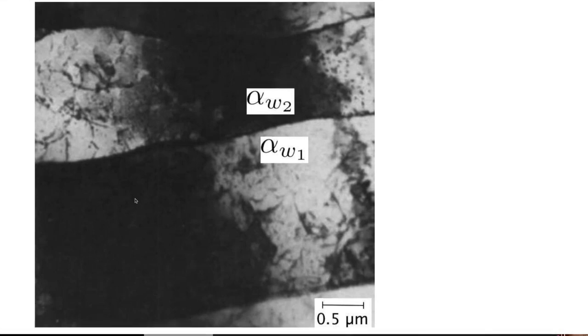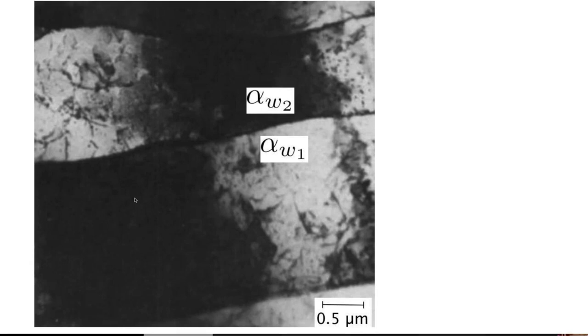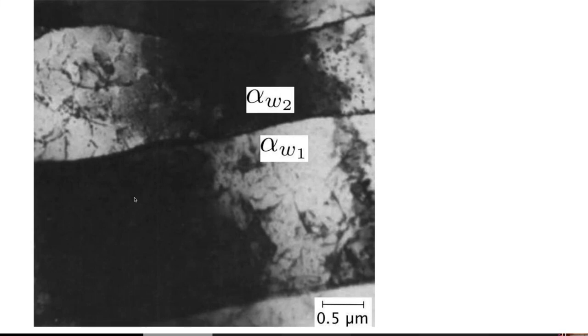Now, you might ask, why doesn't martensite or why doesn't bainite grow by this mechanism? Because they can cancel out each other's strain energy approximately. Well, the reason is there is a cost. There is a cost in growing two plates together, and that is that you have to simultaneously nucleate the correct two plates, which will accommodate each other's shape deformation. And that is unlikely compared with the nucleation of single plates. So you greatly reduce the nucleation rate, and that means that you get a coarse microstructure. And a coarse microstructure is not good for toughness. So very often in, for example, weld deposits and so on, we try to avoid Widmanstätten ferrite, and I'll show you how to do that.